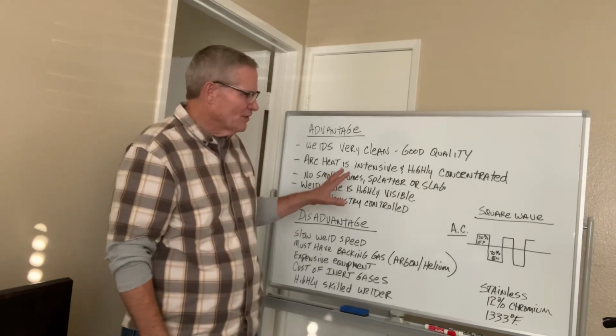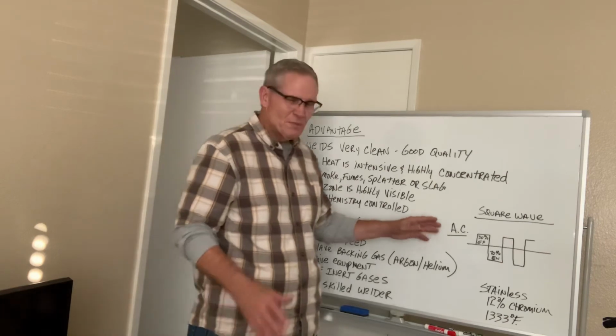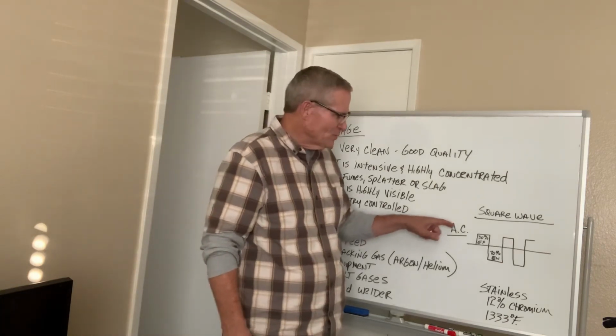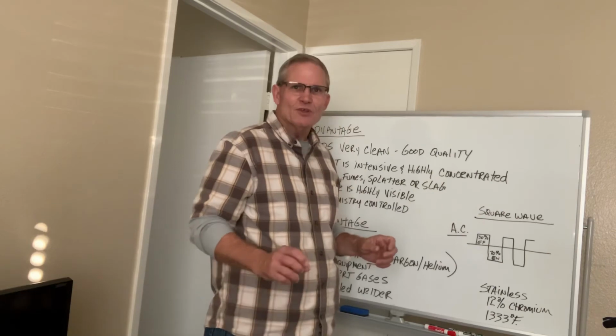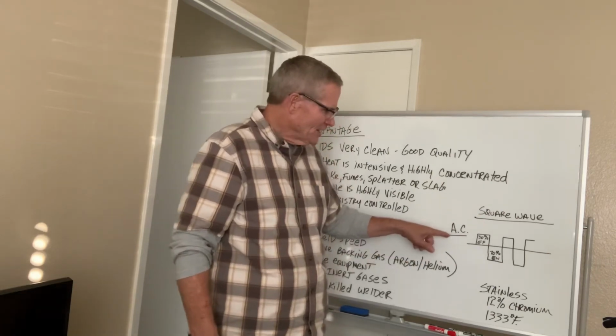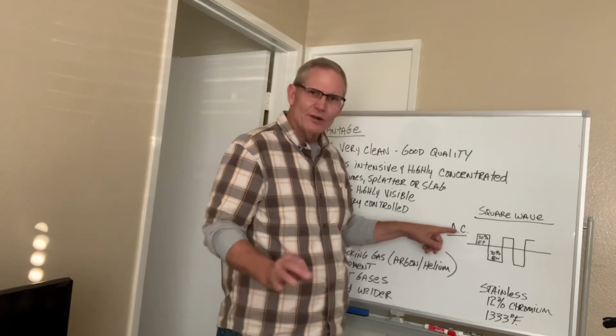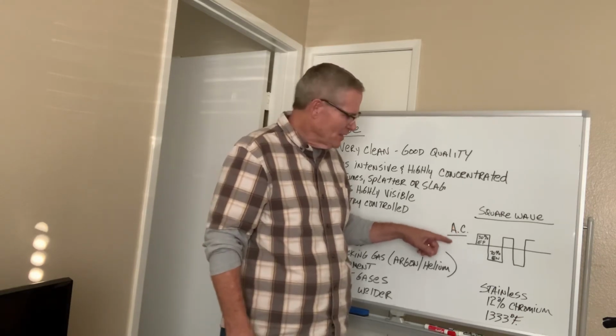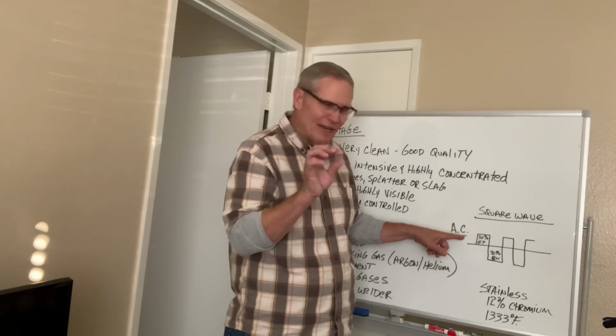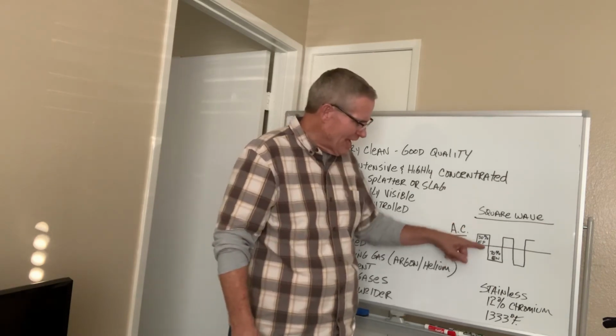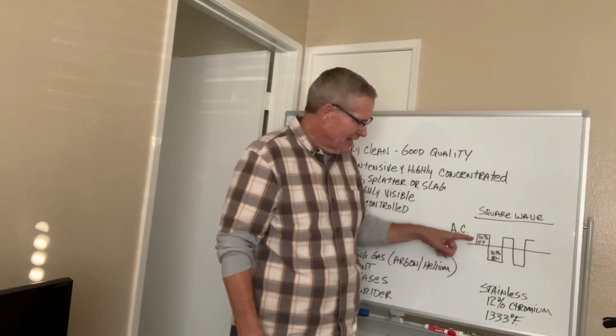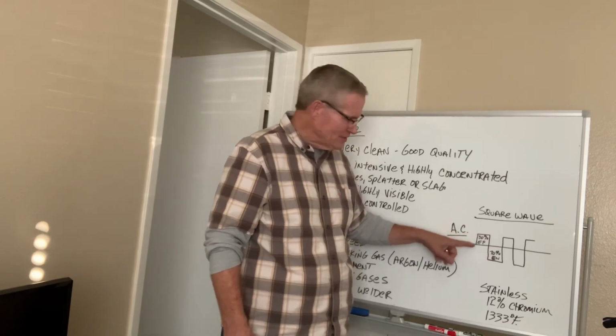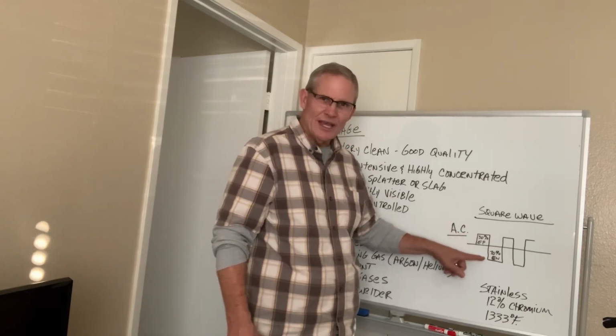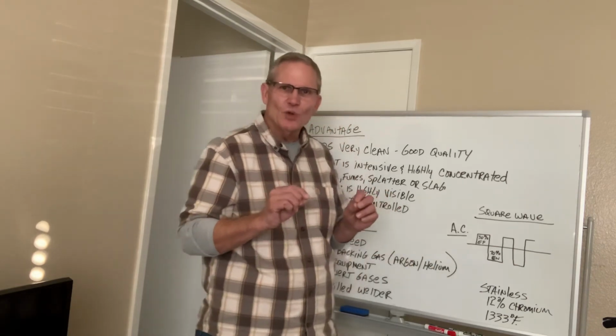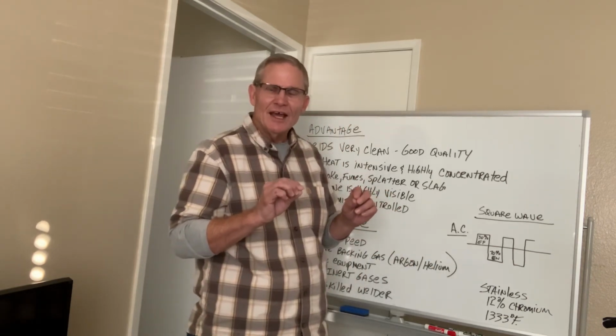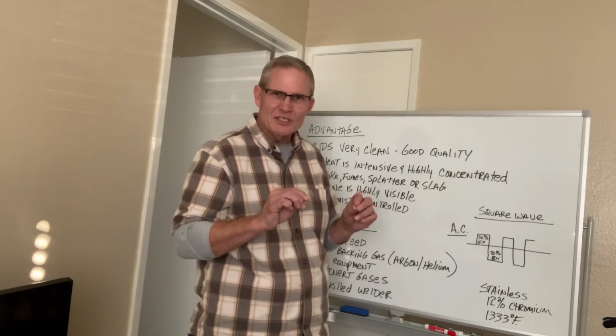The other thing with this particular process, particularly when you weld aluminum, is something called square wave. On the square wave machines, and this is alternating current welding aluminum, they allow you to dial in how much of the half wave of the alternating current is on the electrode positive and how much is on the electrode negative. And what this does is it controls the heat penetration onto the metal itself.